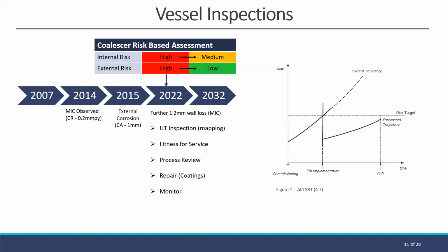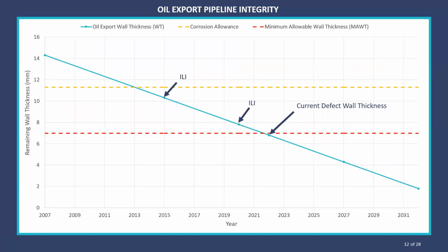So the written scheme of examination looks something like UT mapping to gain the remaining wall thickness, a fitness for service assessment, potentially a process review looking to downrate this vessel to allow repairs focusing on external first, and then an intrusive inspection to repair the glass flake lining when the shutdown permits. And then we would monitor this throughout life.